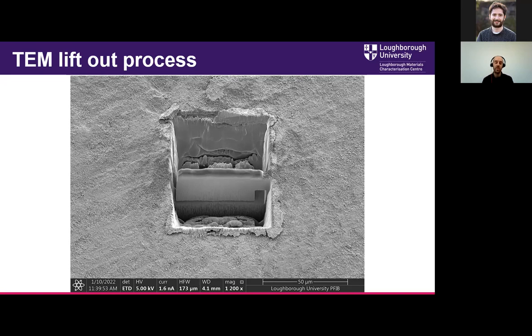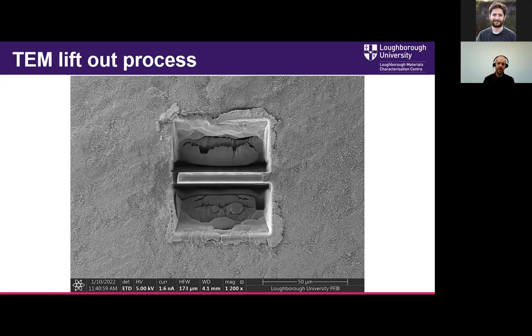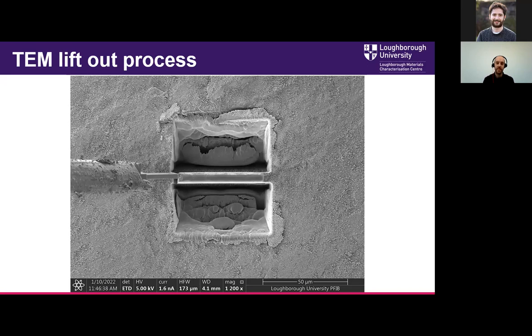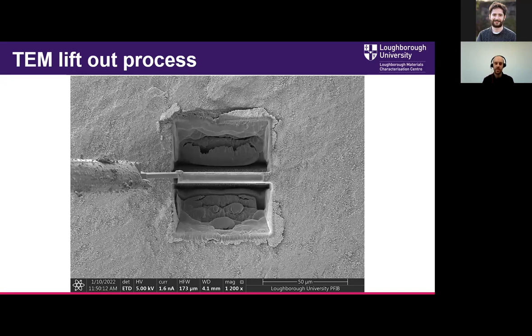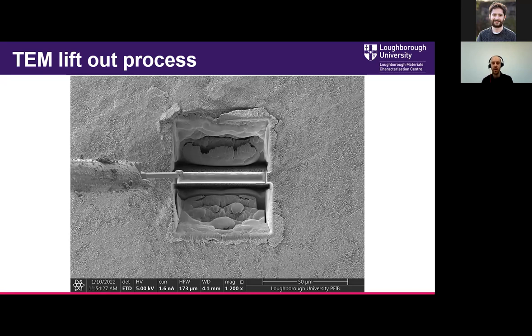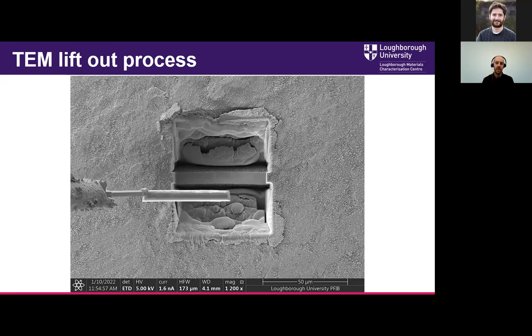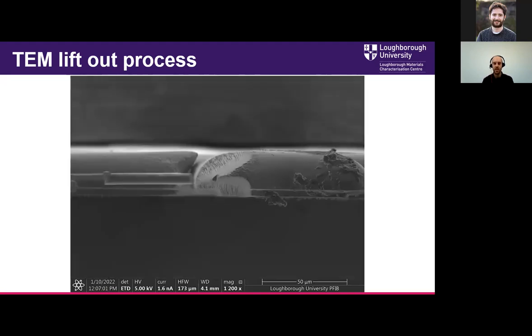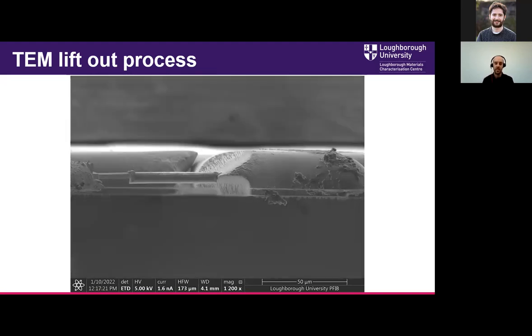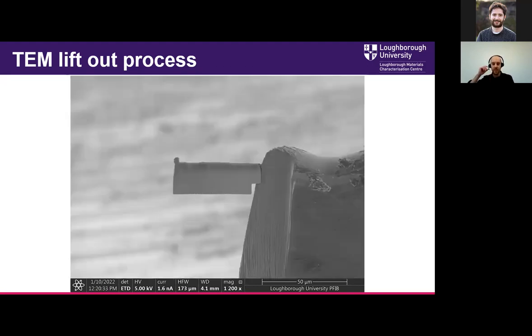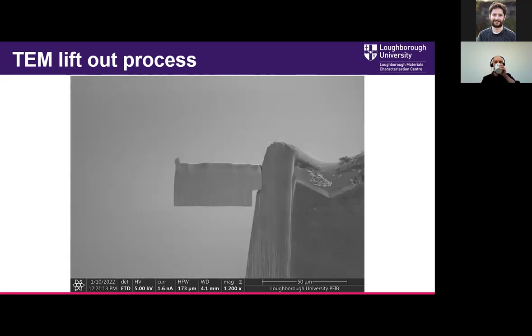And then we could bring in one of these probes I was discussing, and we could pick up this TEM lamella. So here we are bringing in the probe, welding it on with some platinum or tungsten, and then we would cut the edge of the sample off and lift it out of the bulk. Once we'd lifted it out of the bulk, we could put it on a copper half grid. This is a copper half grid, and we just place it on the grid and weld it onto the grid, and then we could polish it down until it was electron transparent and use it for TEM. We won't show the polishing, it's a little bit long-winded.